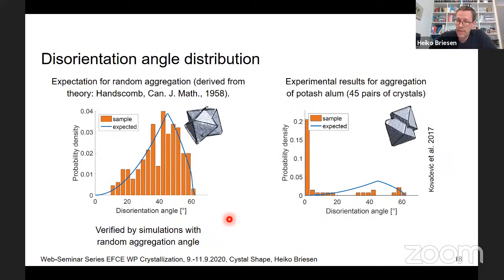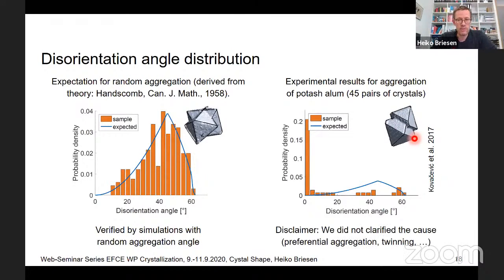So there are a limited number, only 45 pairs of crystals, but we hardly observed any larger disorientation angles, and the huge set of crystal aggregates looked similar to this one, very much oriented towards each other. Short disclaimer at this point: I do not say that we're able to clarify whether this is caused by preferential aggregation or by some twinning of crystals. Could be any of those. We just had this observation at the moment that the disorientation angles are not distributed in a way as would be expected when you have a random orientation at aggregation. This is all we can detect here.